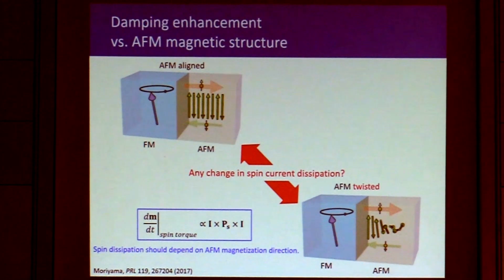The other thing we can do for the antiferromagnet is change the antiferromagnetic order. Say right now it's all aligned in the ferromagnetic moment direction. But what happens if we twist the antiferromagnetic order? Based on this spin torque equation, we should observe an additional damping enhancement.